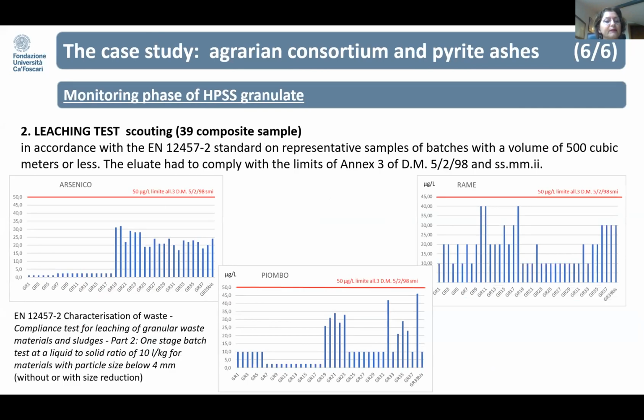Then here you can see the results of the verification protocol of the leaching test, and the protocol provides for analysis of 8 polluting elements present in the soil. Zinc, cobalt, vanadium, and cadmium have always resulted below the detection limits, while only 3 elements shown in this graphic show quantity above the detection limit in the leaching test. We are talking about arsenic, copper, and lead. In any case, all the results were below the limit for waste recycling.